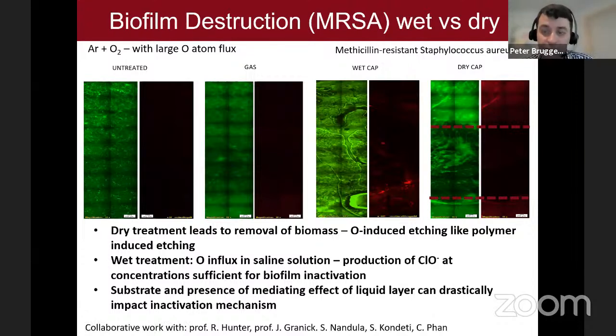And so these are actually two different modes. Quite interesting, the dry case, what actually the plasma is doing, we have an oxygen plasma. The O atoms are etching away the biofilm, like they would etch a polymer, for example. And in the wet case, there is no etching because the species go to the water, you produce chemistry, and there is a chemical action of the inactivation of the biofilm. So even very similar systems can kind of lead to completely different kind of processes that are enabling these biological interactions. But again, this is just initial work, and there's probably still several years that we will be working on to get a deeper understanding.